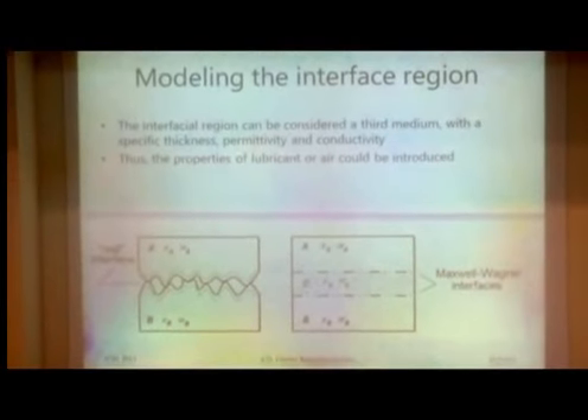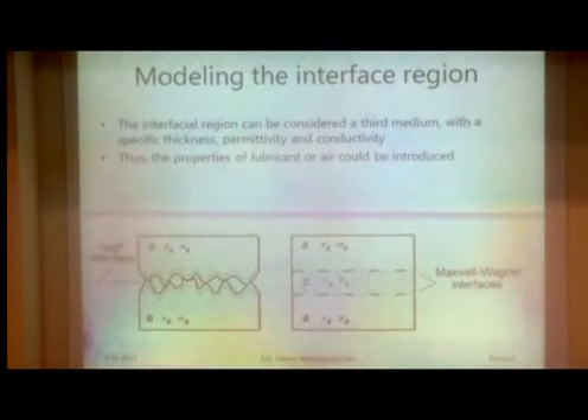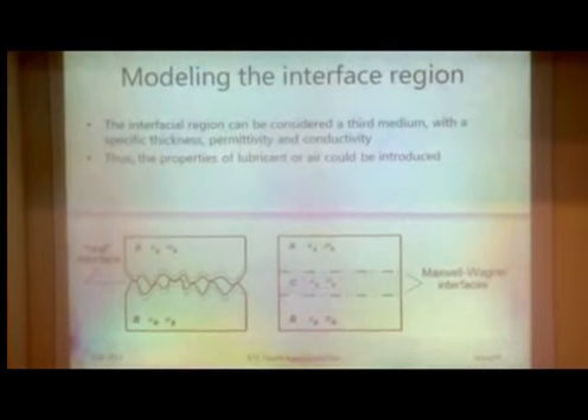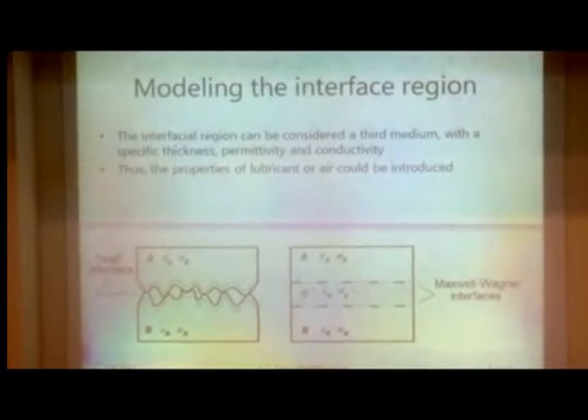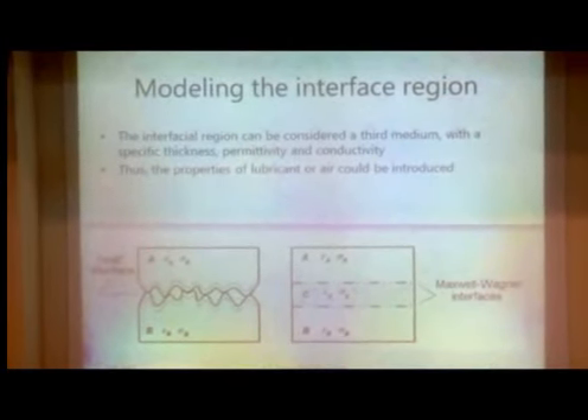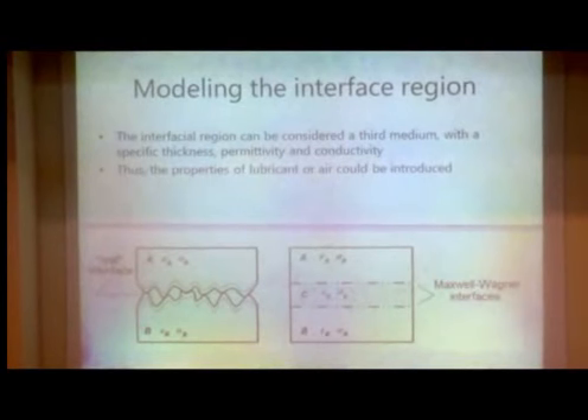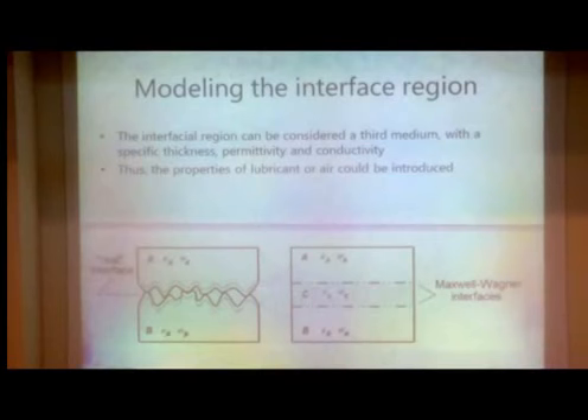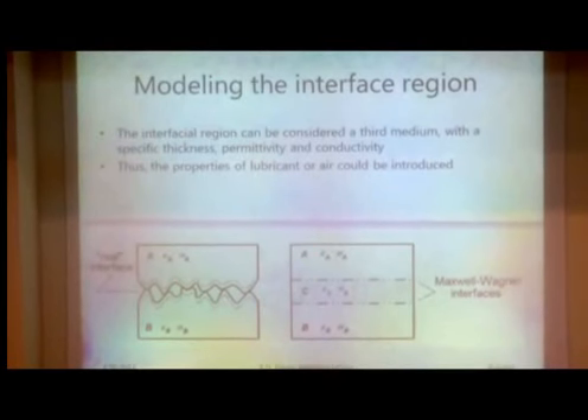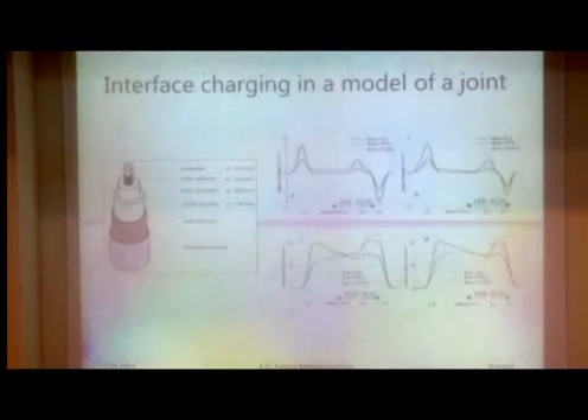Now, then we have the interfacial region. If we have a mechanical interface, we have to model in some way the properties of the medium we don't know, the uncertainties. So you could introduce a third layer, for instance, a silicon oil layer which matches the two media. And you can use a 3-layer Maxwell capacitor. Okay, let's have a look at the results.